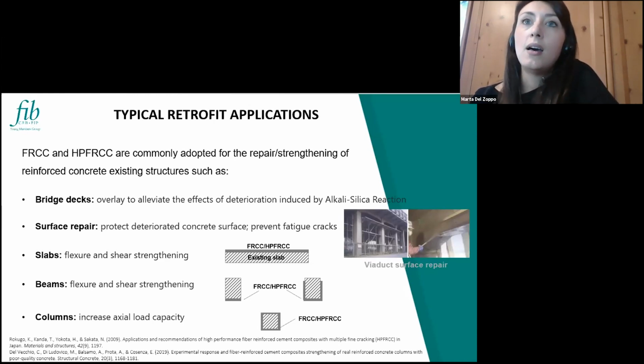So basically, this kind of approach is used for structures in aggressive environments like cold regions, offshore structures, and also dams. But they are also used as a protection, a surface repair, to prevent fatigue cracks, because of course we have a higher crack control. So in structures like viaducts or bridges, we can control the cracks thanks to this advanced control given by the